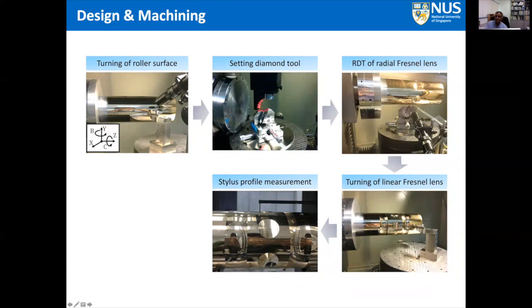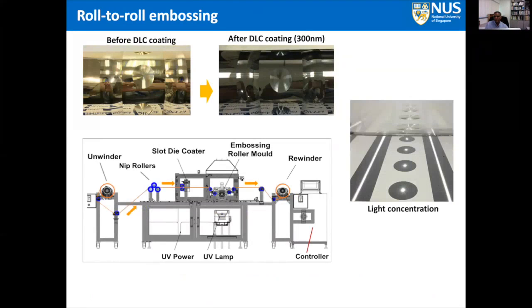So these are the different types of lenses; the radial lens as well as the linear Fresnel lens are produced. And then we directly machine them on the mold or on the roller, which will be used for printing. After we make it, we also apply diamond-like coating on the lenses, especially on the roller. This is to prevent wear, so that we can use it for a longer duration. And we will just mount it, and then we can produce these kind of interesting lenses, which are observed on the right hand side here. Okay, so this is the image at the end of the day.